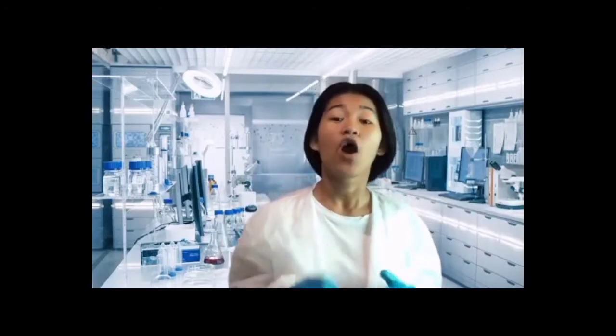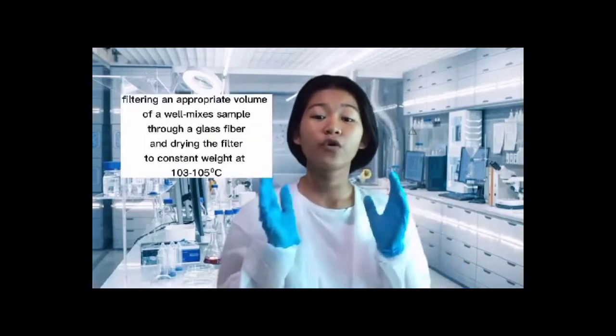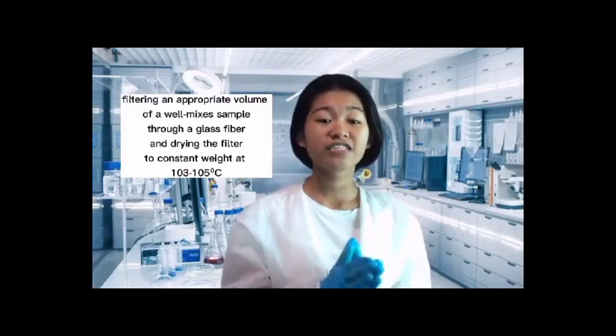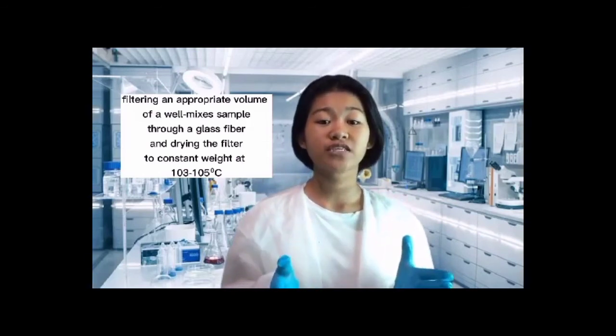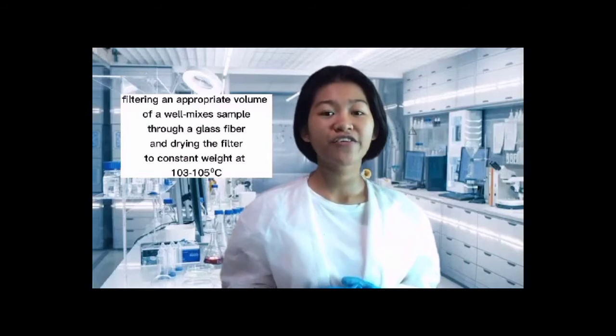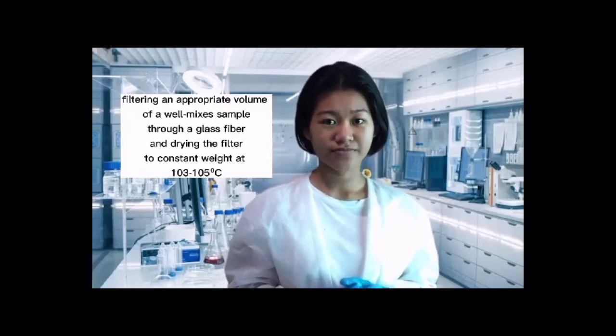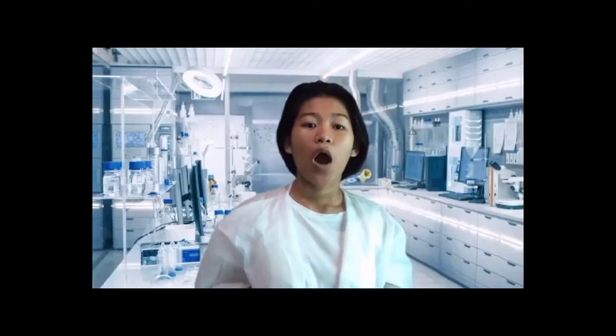The analysis for suspended solids in water samples, for example, is accomplished by filtering an appropriate volume of a well-mixed sample through a glass fiber filter and drying the filter to constant weight at 103 to 105 degrees Celsius. Consequently, particulate gravimetry is not easily extended to the analysis of trace level analytes. Particulate gravimetry uses the same balances as other gravimetric methods and is capable of achieving similar levels of accuracy and precision.